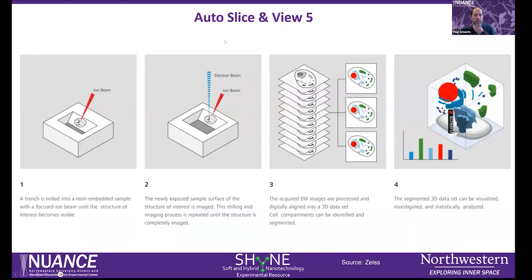The Auto Slice and View software is basically a software for 3D imaging or 3D analytical EDS EBSD data. In this approach, you create a region, carving it out with the ion beam, removing a small slice of material, and then exposing it to electrons to collect various signals and create an image of your cross section. If you repeat that multiple times and layer the images together, you can create a 3D visualization of the volume that you removed.